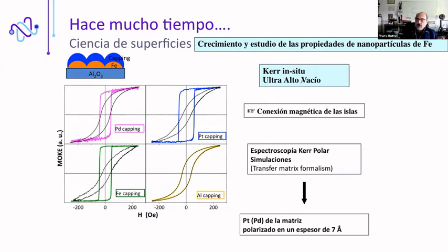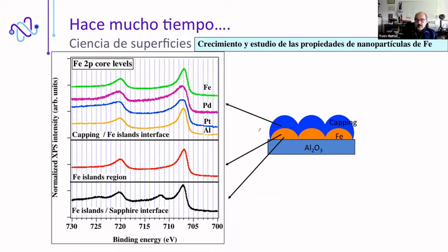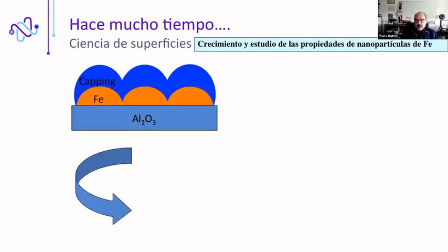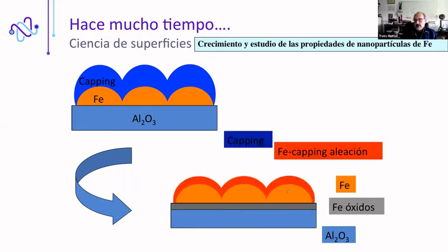Then we wanted to know more about the structure of these nanoparticles. And we performed XPS at different depths of the system. And we can focus only on this red curve, which was measured here in the middle of the iron nanoparticles, and on the black curve here, black spectrum, that was measured close to the interface with the sapphire substrate. As you can see, there are two more peaks here in this photoemission spectrum. And these peaks belong to an iron oxide. This means that our system was not that simple, that it was not made of iron nanoparticles with a simple capping. It was more like this one with a sapphire, iron oxides, iron, then a layer that was polarized or probably an alloy with the capping layer.